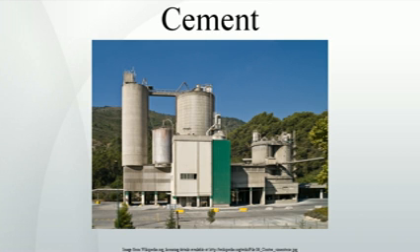Non-hydraulic cements such as slaked limes, calcium hydroxide mixed with water, harden due to the reaction of carbonation in presence of the carbon dioxide naturally present in the air. Calcium oxide is produced by lime calcination at temperatures above 825 °C, 1517 °F, for about 10 hours at atmospheric pressure. The calcium oxide is then slaked by mixing it with water to make slaked lime.